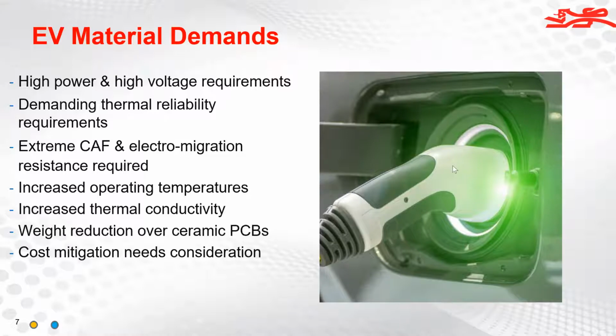The temperatures, obviously, they're going to increase with this high energy in the board. We've seen temperatures up to 160 degrees C, and there's discussions of all the way up to 200 degrees C during operation in a cyclic manner. So the material has to be able to handle those temperature cycles as well as peak temperature operating conditions on the vehicles and in the systems that are charging these vehicles.